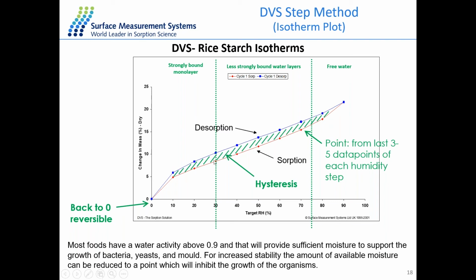And there is a gap between sorption and desorption. This is called the hysteresis gap, and this is because it has very high uptake of the water molecule, and those water molecules are not just on the surface. They will penetrate the surface and go to the bulk of the material. So during the desorption part, when the water molecule desorbs from the bulk, it is a diffusion limited process. So this hysteresis gap confirms this moisture sorption mechanism is a bulk sorption dominating mechanism.